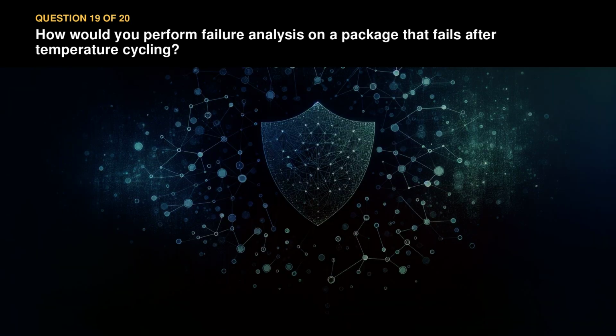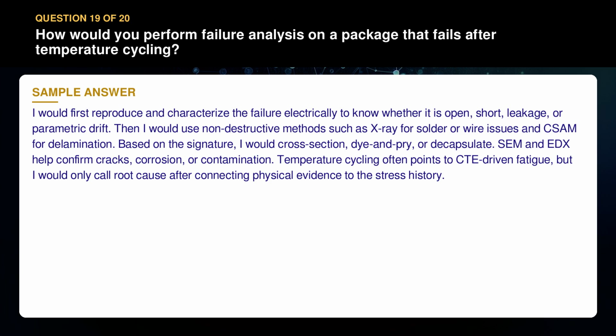Question 19. How would you perform failure analysis on a package that fails after temperature cycling? I would first reproduce and characterize the failure electrically to know whether it is open, short, leakage, or parametric drift. Then I would use non-destructive methods such as X-ray for solder or wire issues, and CSAM for delamination. Based on the signature, I would cross-section, dye-and-pry, or decapsulate. SEM and EDX help confirm cracks, corrosion, or contamination. Temperature cycling often points to CTE-driven fatigue, but I would only call root cause after connecting physical evidence to the stress history.